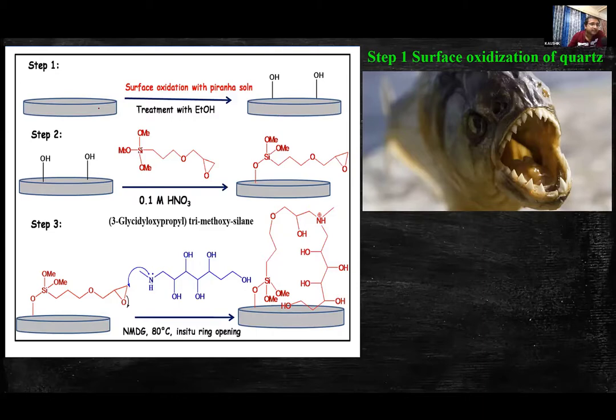So the first step is the surface oxidation. This surface oxidation of the quartz sample support has been carried out using piranha solution. Piranha is a 3:1 mixture of sulfuric acid and 30% hydrogen peroxide. It is a strong oxidizing agent, which oxidizes the quartz sample support.